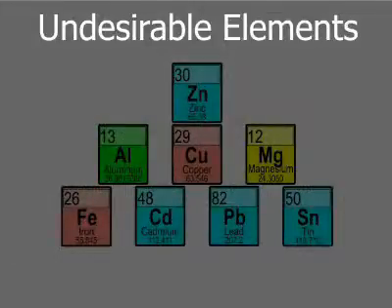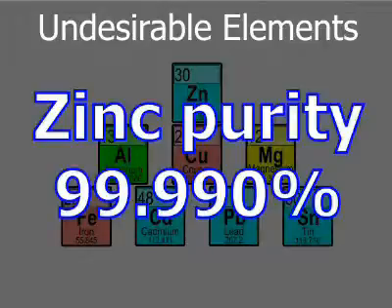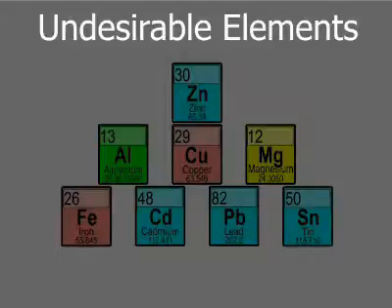These high-purity limits can be maintained only by using special high-grade zinc with a purity of 99.99% as the base zinc. Suppliers, through many years of development, routinely produce primary metal that meets the purity standard. All of the zinc and ZA alloys produced in the US and Canada are made from primary metal that meets the purity specification.